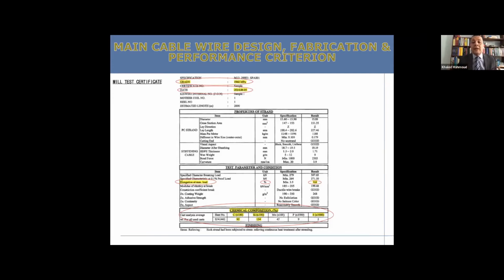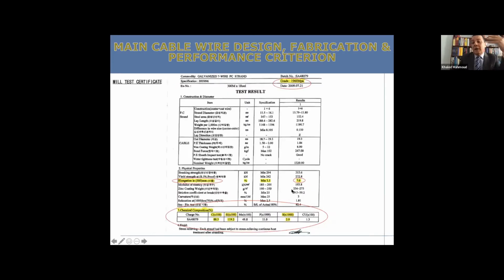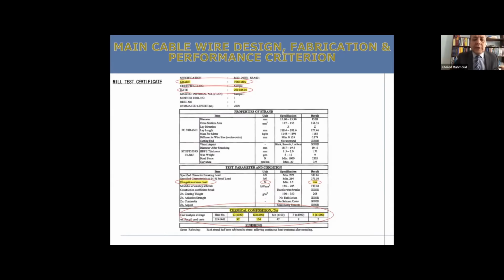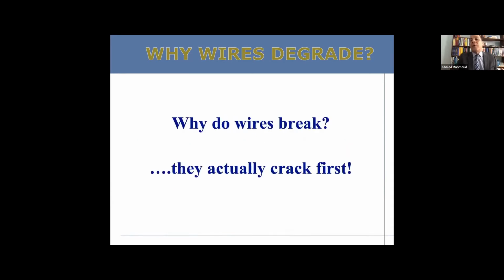elongation capacity. And what matters here is, or the difference comes about the change in the chemical composition. You see that the carbon content and the silicon content are higher for the wire that has lower or reduced capacity of elongation. What does that mean? Why is that important? That's important because these chemical compositions have a lot to do with how the wires break.